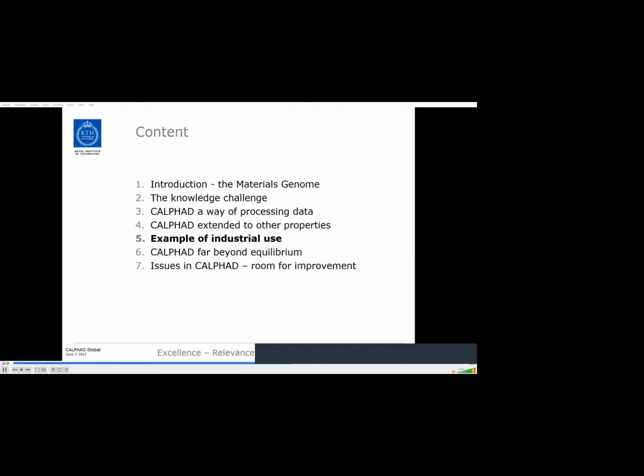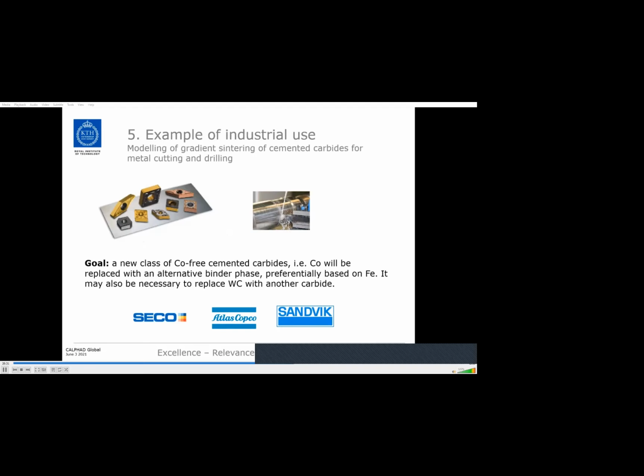So let's now consider an example of the industrial use of materials genome and CALPHAD. This example concerns modeling of gradient sintering of cemented carbides for metal cutting and drilling. And metal cutting and drilling, well, metal cutting are typically done with this kind of tools. And this is a collaboration between three Swedish cemented carbide producers and KTH, and the work is done within the Hero-m center. So the goal here is to produce a new class of cobalt-free cemented carbides. Cobalt will be replaced then by other phases. The reason is that cobalt has a number of issues.